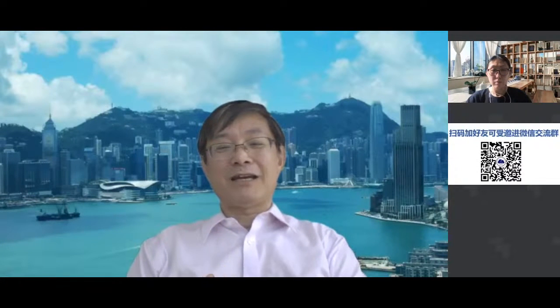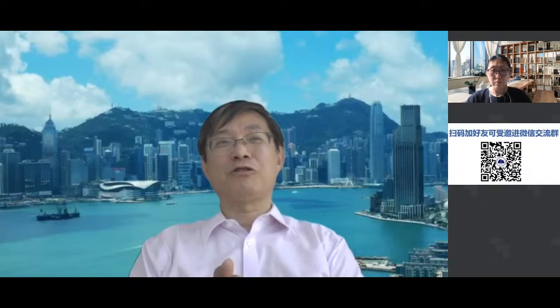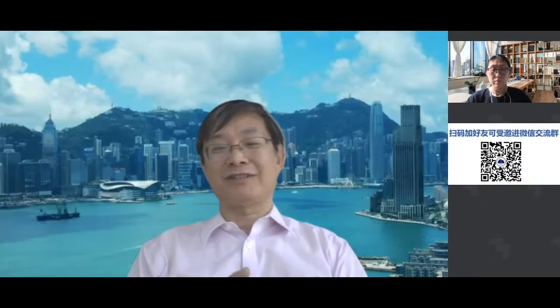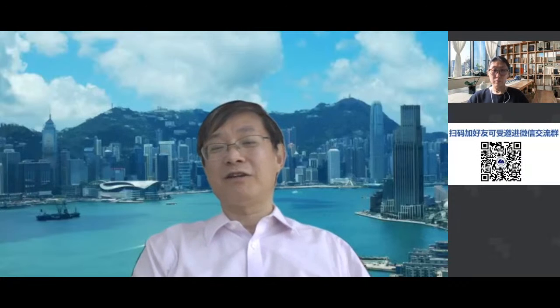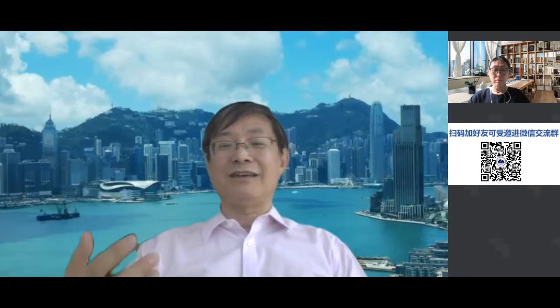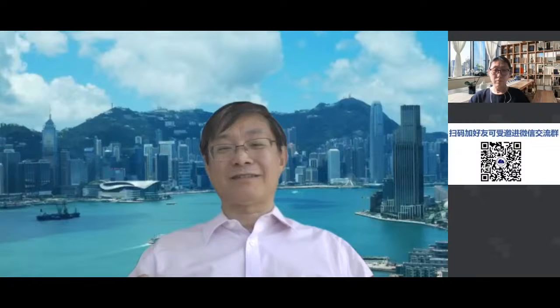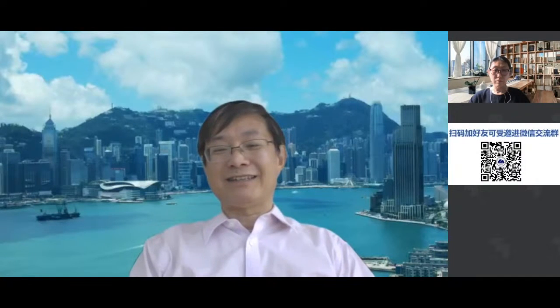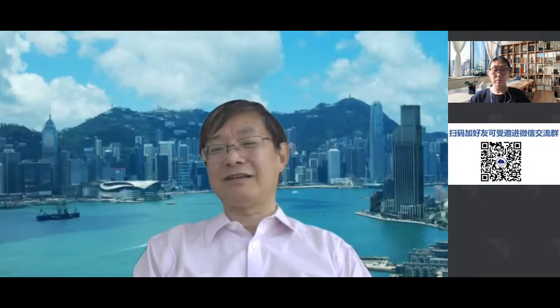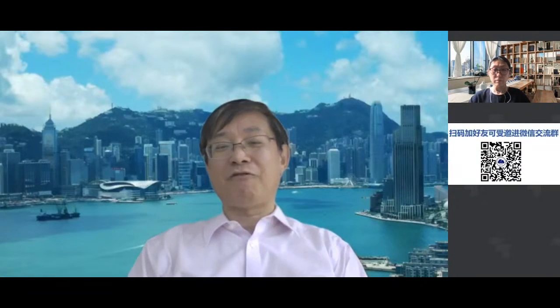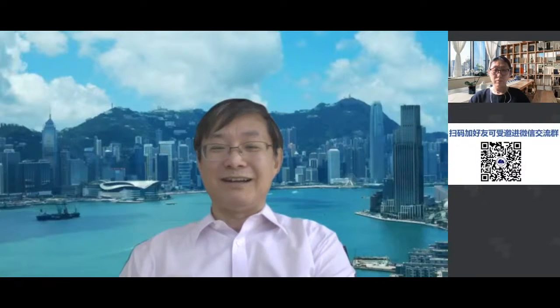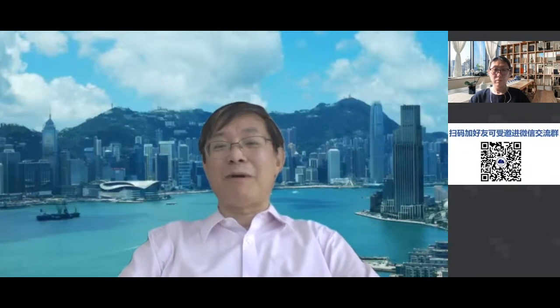With PVD, we can change a lot of condensation conditions. So for this reason, we should choose a material that can switch easily between the crystal and the glass. Then by changing the processing, you can fabricate the dual phase material more easily. So the concept is slightly different. Before, we always tried to have so-called high glass formability material.